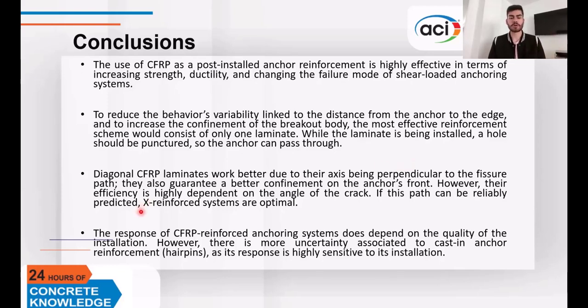X-reinforced specimens work really well, but their effectiveness depends on how well the crack orientation is known. If it is possible to reliably predict the angle of the cracks, then X-reinforced specimens are optimal.